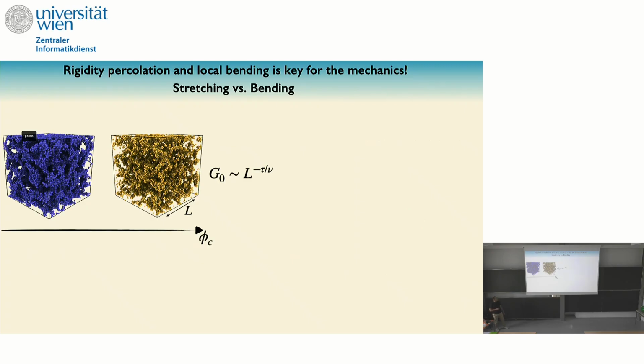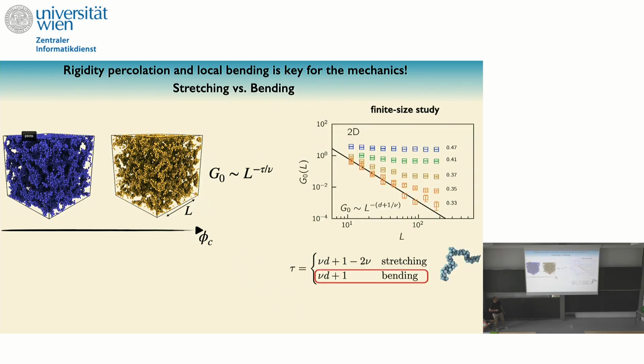But still you can do this game by taking just a small system, changing the size and going towards the critical volume fraction. And what you see is that the modulus scales very well with the system size. And the exponent that you get once you approach your critical point is the one that you expect from the bending dominating. So all the linear elastic properties of your system are dominated by this length scale, but also by the bending at the level of your strand. And this is an effective bending that arises from this structure that would form naturally in your system.